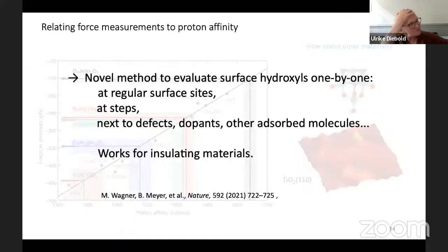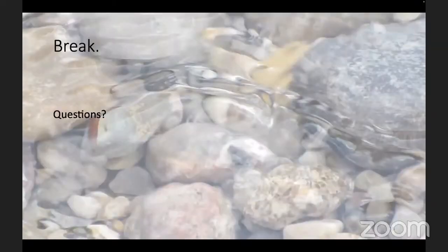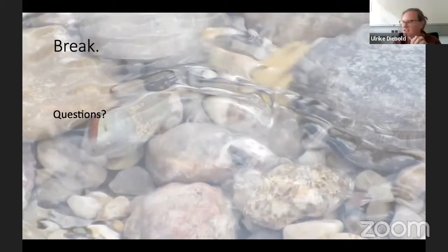So that's the first part I wanted to show: we have found a novel method to evaluate surface hydroxyls one by one. In principle, we can do that at regular sites, and show that these are heterogeneous surfaces. Our dream is to do that at regular surface sites, at steps next to defects, dopants, other molecules, and so forth, and really figure out the proton affinity of oxygen atoms in different oxides, and then hopefully give some kind of benchmark to theoretical calculations. So this is where surface science stands at this point.